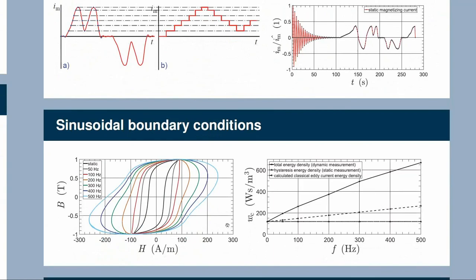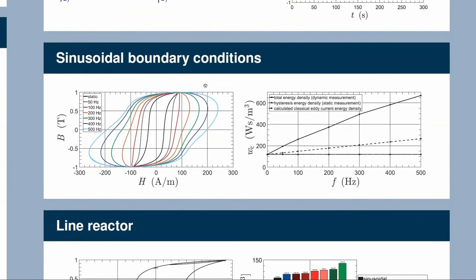I first tested under sinusoidal conditions and measured under dynamic conditions. With increasing frequency, the areas of the dynamic hysteresis loops increase because the energy density is a function of dB/dt. When measuring with the static measurement setup, you can measure the static loop, and this represents the static hysteresis loss density.